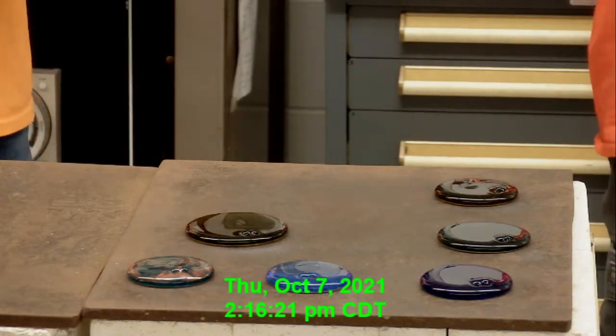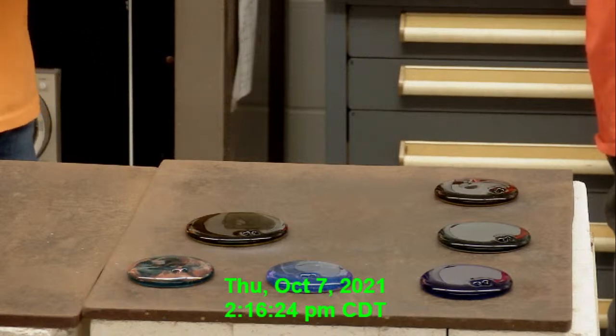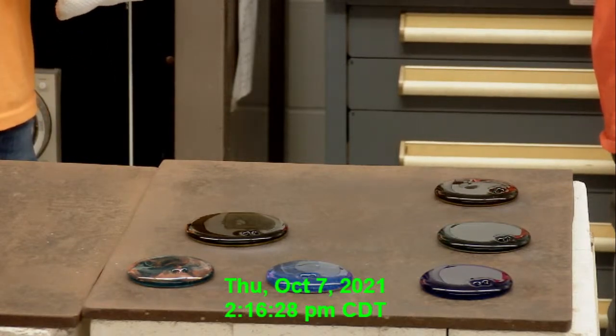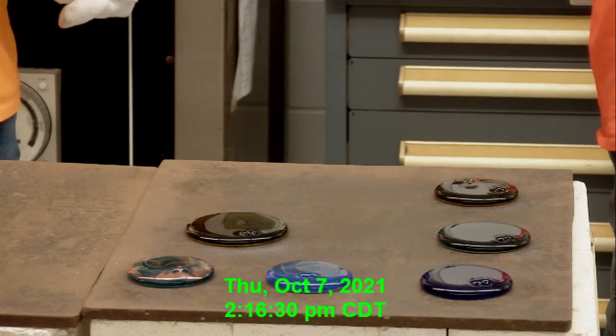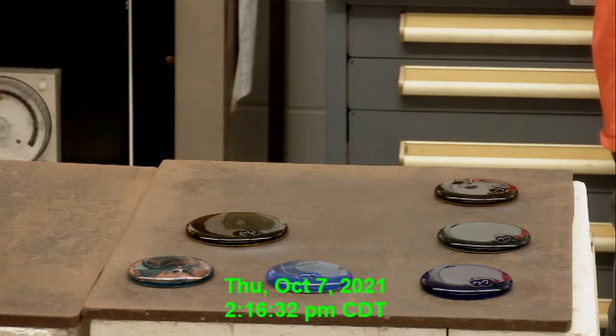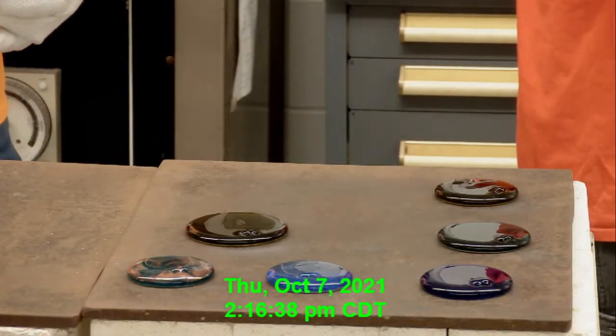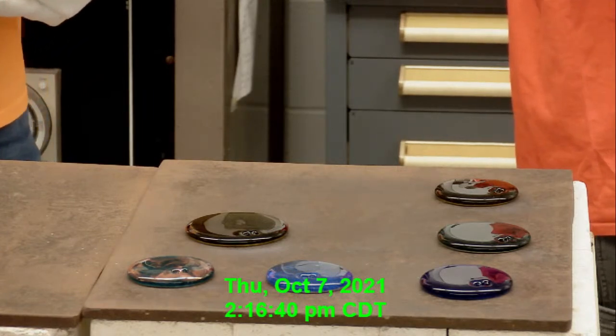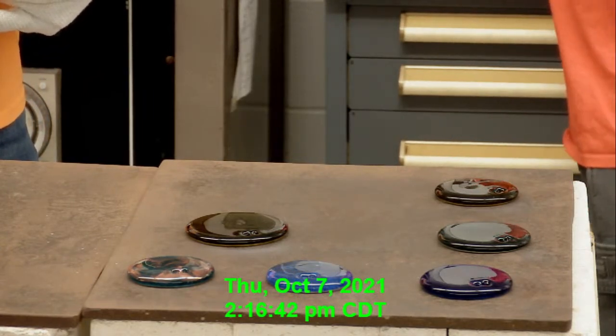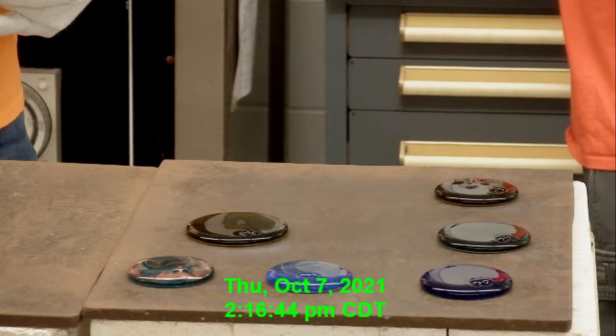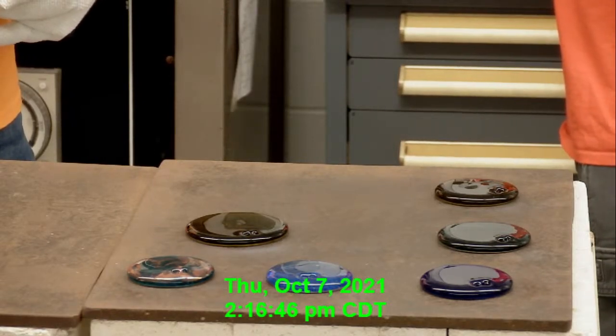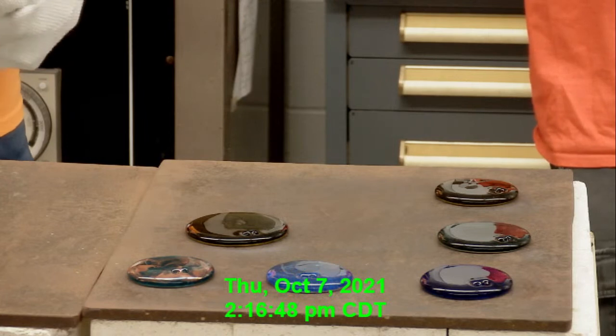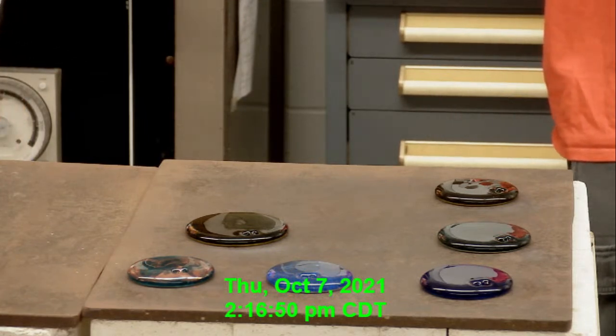Composition S1. This one is mostly purified silica, some whiting, a little bit of white sand, 10 grams to 80 grams. Sodium carbonate, washing soda, calcium carbonate, dolomite. First example of dolomite. That's a calcium magnesium. We've got 0.2 gram loading of chrome oxide. This should be green. Kind of the 7-Up bottle green, at least it usually is. And 1 gram of sodium sulfate.